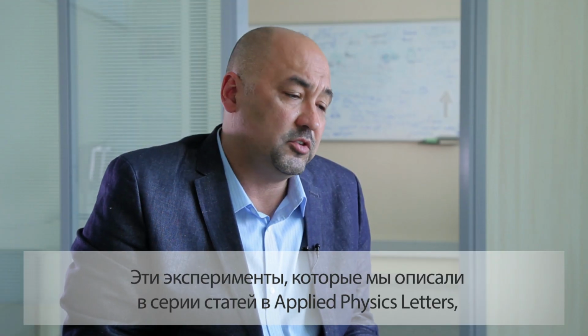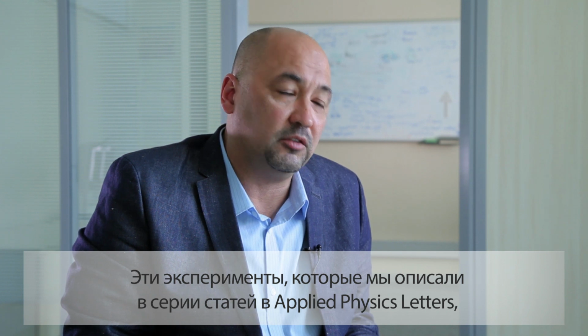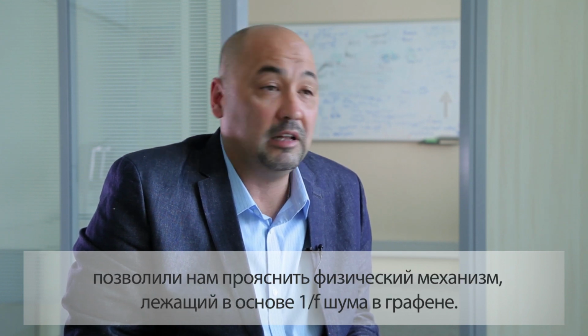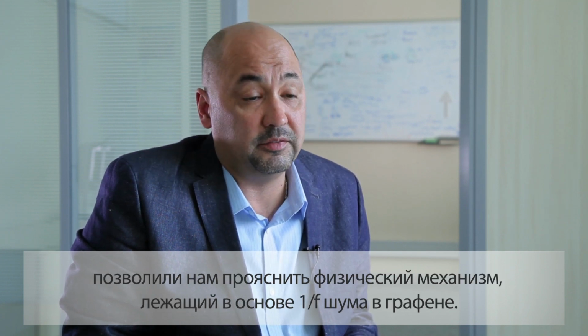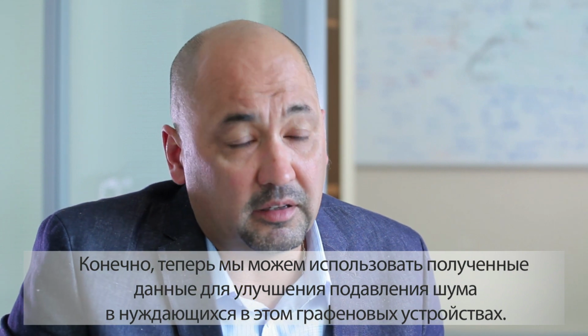So these experiments, which we described in a set of papers in Applied Physics Letters, allowed us to clarify the physical mechanism behind 1/f noise in graphene. So it is more related to fluctuations in the mobility of carriers rather than fluctuations in number of carriers in graphene channel. Of course, using this data, we can now further reduce the noise level in graphene devices where it's needed.